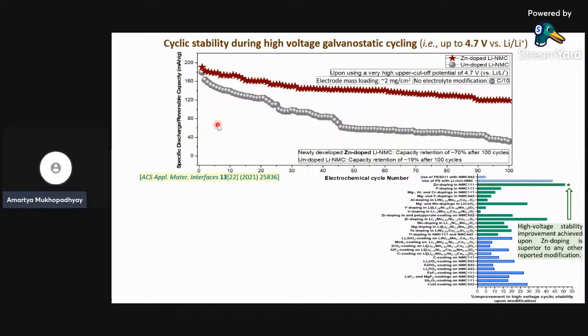Now, we cycled up to 100 cycles for the undoped and the zinc doped material using an upper cutoff of 4.7 volt. Now, I should mention here that 4.7 volt is more of an academic interest because the electrolytes start degrading and a lot of capacity fade is also attributed to the electrolyte. But these are very similar cells with the same electrolyte, etc.